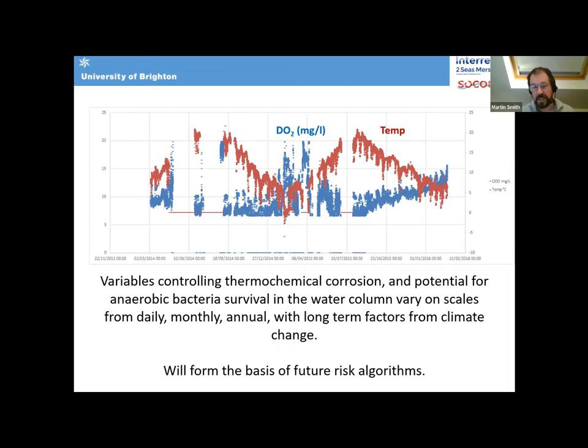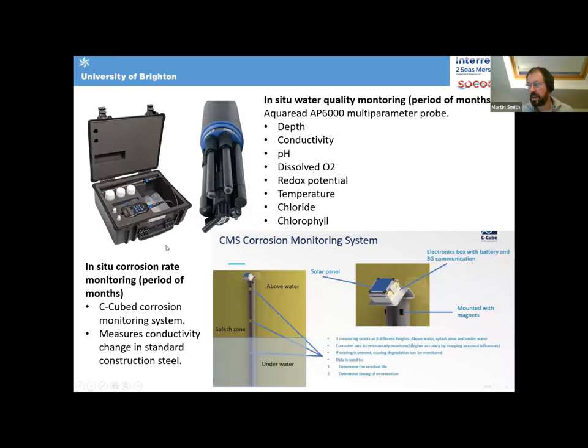These kind of data have been used in laboratory experiments now to try and build an algorithm that links to corrosion rate. And the next phase we have for field monitoring is we're actually going to install in-situ water quality monitoring to look at conductivity, pH, dissolved oxygen, redox potential, temperature, chloride, and chlorophyll, alongside monitors that will directly measure conductivity change in a steel strip, so we can relate those factors to corrosion rate.